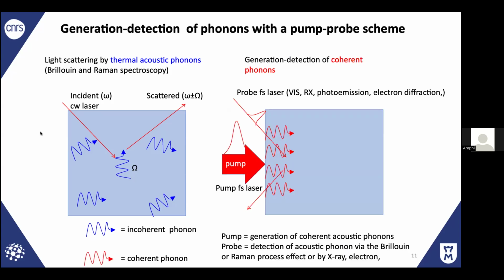But in our case, what we discuss is that situation. We actually use a light pulse. There are different kinds of processes. We excite electrons, etc. And then by different mechanisms I will discuss, we can emit such a phonon. There is a given phase relation for all these phonons that gives rise to a wave packet of phonons. And we say that these are coherent phonons. Of course, we generate them with light, and we can detect such phonons by different techniques, let's say visible, or X-ray diffraction, photoemission.